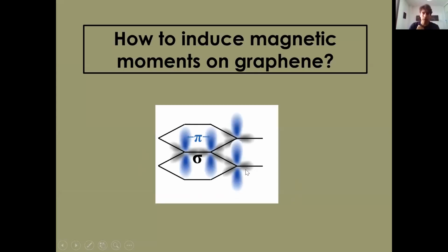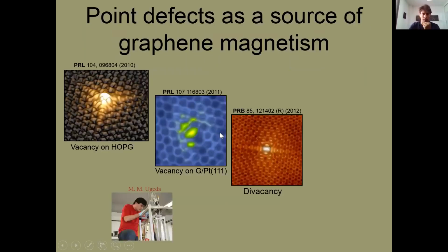So from a theoretical point of view, the answer of how to induce a magnetic moment is very clear. That's the bonding schematics of graphene. And the only thing you need to do is to remove this pi electron. If you are able to remove this pi electron, this blue guy that I have plotted here, then you will have an unpaired electron on the graphene network, and a magnetic moment will emerge. Always when you have an unpaired electron, you have a magnetic moment.